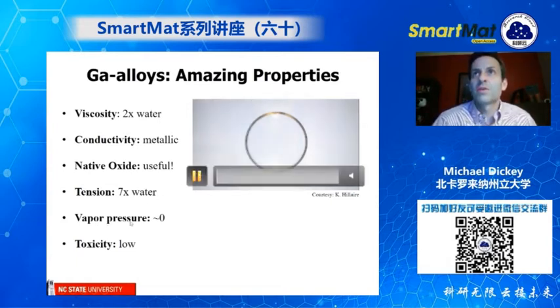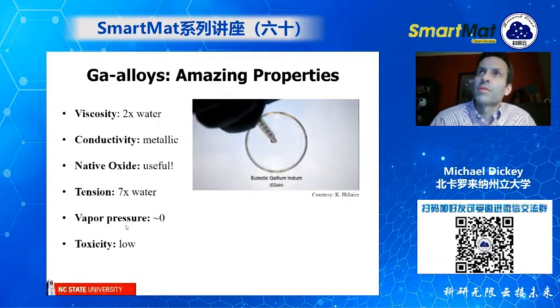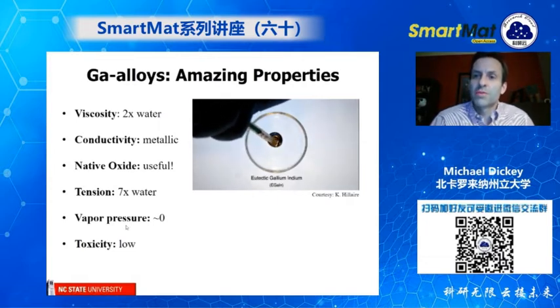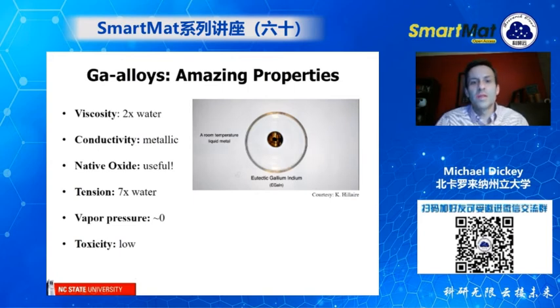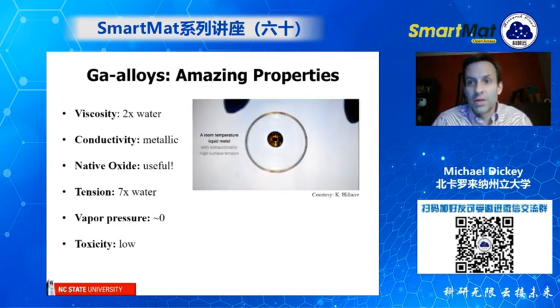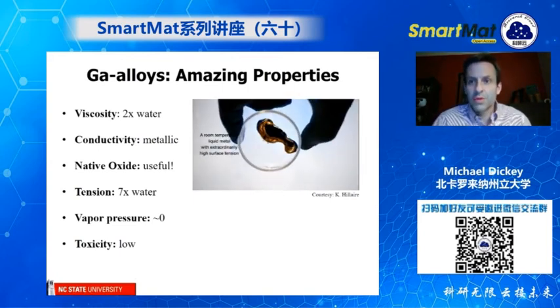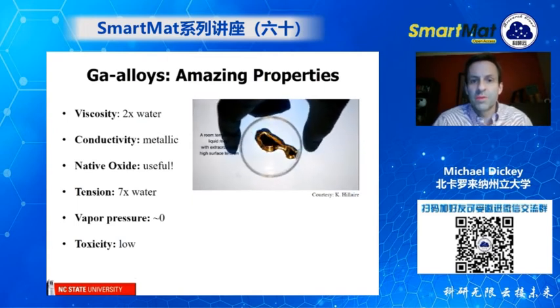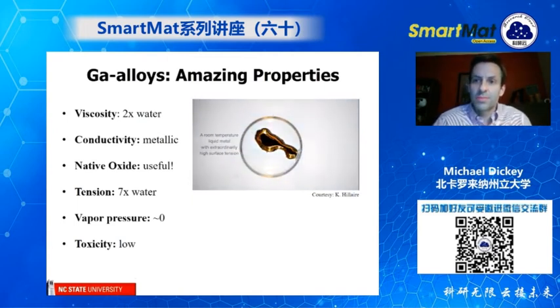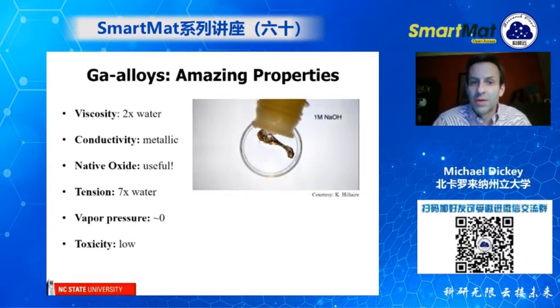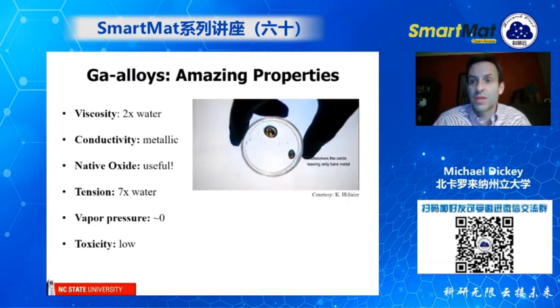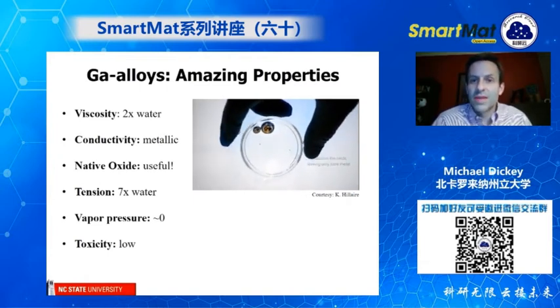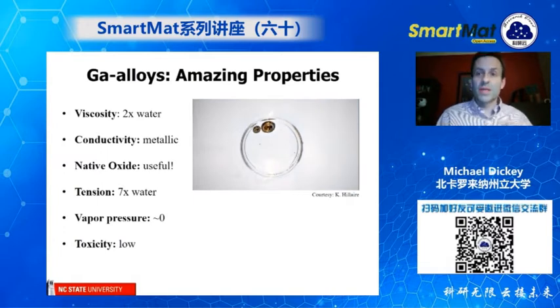So let me show you this video. This is a little bit of the liquid metal being squirted out from a syringe, and you can see that it flows very easily because of the low viscosity. If you swirl around the container, you can see the liquid flows, but it holds this kind of weird shape, and that's due to this oxide layer. Now, if you dissolve away the oxide layer, the metal will simply bead up due to surface tension. So we do that using sodium hydroxide, which is a base. So this is kind of a really key idea, is that this metal reacts with air and forms a very thin oxide on its surface.